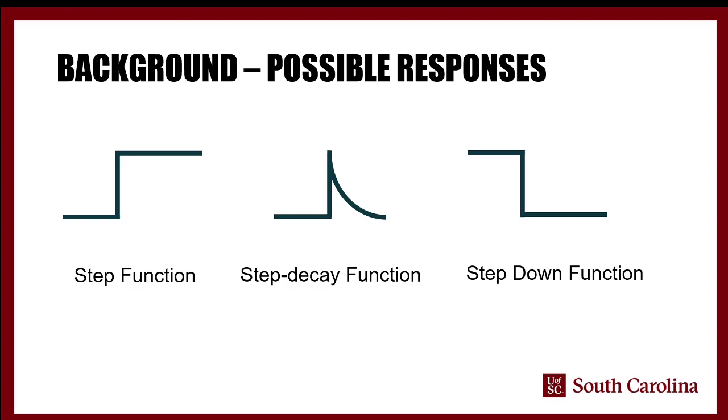For instance, you could try to detect a molecule of DNA, a particular chemical species, by choosing your ultramicro electrode material such that it is very catalytically active, and once one of those other molecules attaches to the surface, that catalyst site is blocked, and you observe a decrease in the current flowing, because now your catalyst has less active area, and so you have less overall current.